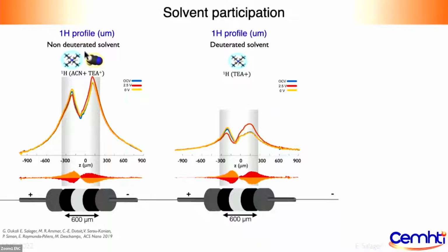And we did this test also with protonated solvent to see whether we had a macroscopic flux or not. And as you can see, the profiles are much more intense because now we have contribution from the solvents, but the differences are of the same amplitude. And so this is indicative that there is no macroscopic solvent flux inside the electrodes. It doesn't mean that inside each electrode it's not different.